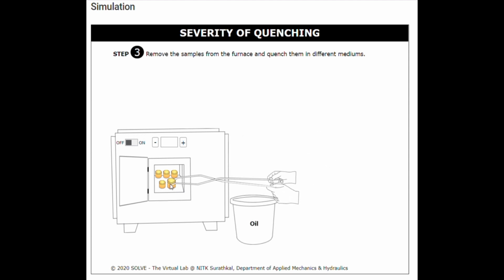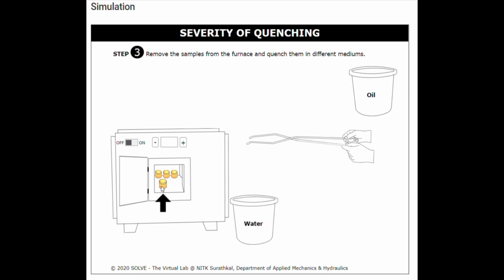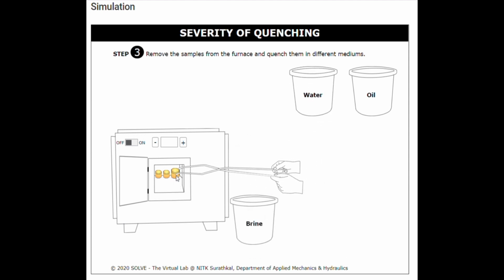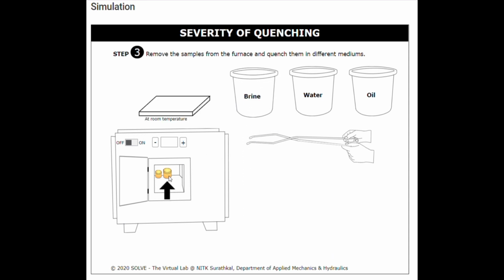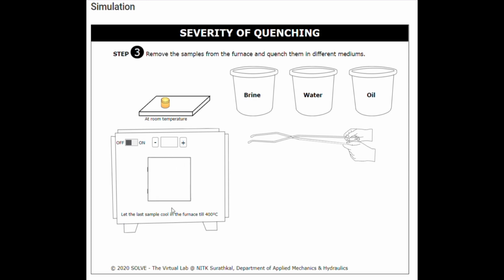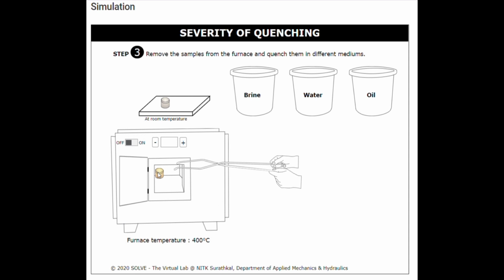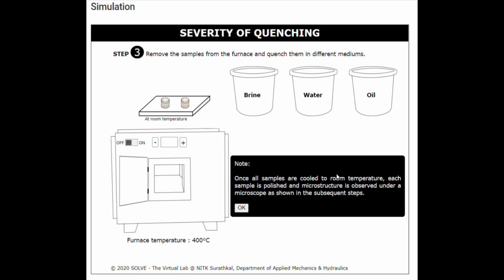First, we put in oil. Second, in water. Third, in brine. Fourth, at room temperature. And the last sample we cool in the furnace till 400 degrees Celsius. All the samples are cooled to room temperature. Each sample is polished and microstructure is observed under the microscope as shown in the subsequent steps.